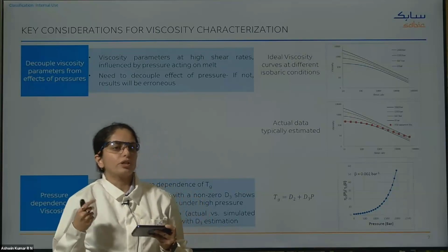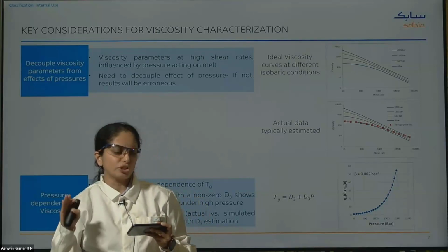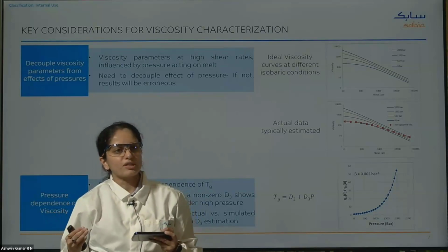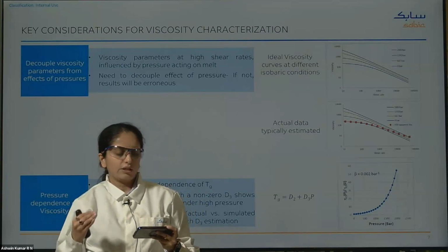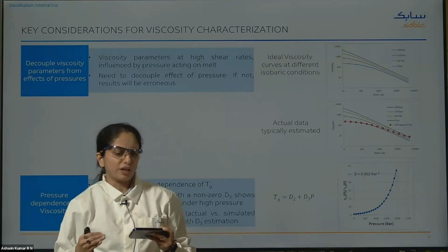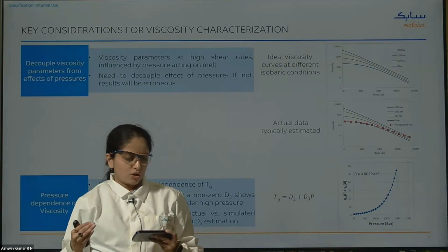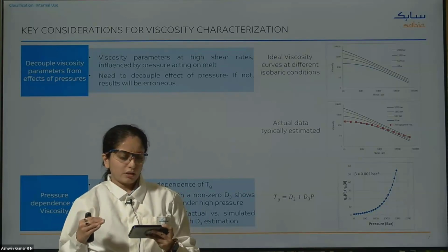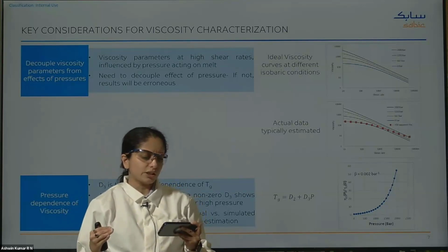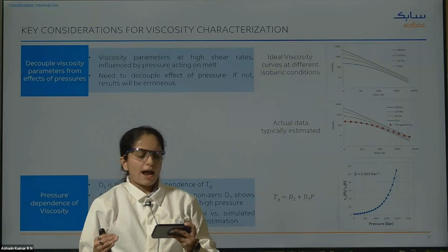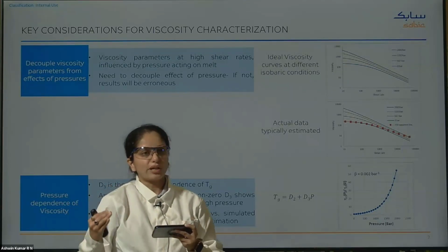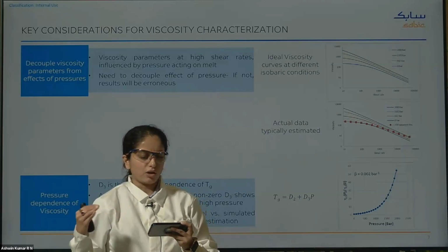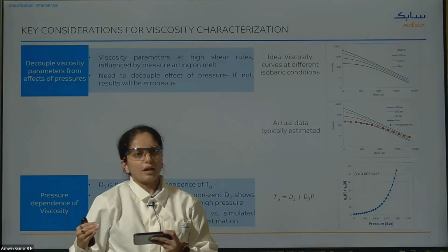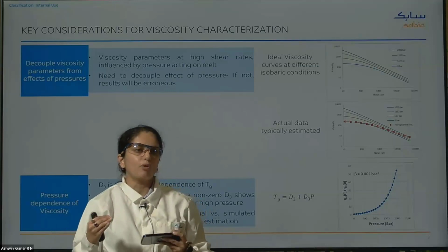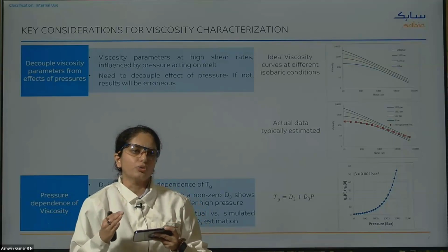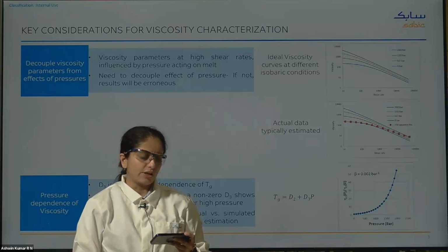I would also like to touch upon the WLF model, which mostly describes the effects of temperature on viscosity. In an injection molding process, when the pressures are above 100 MPa, we need to account for the increased Tg, the reduced free volume, and the effects of pressure. Combining the WLF and the Cross model, we see that the effects of temperature and pressure on the zero shear viscosity are accounted for, and then the effect of pressure on the shear thinning of the melt viscosity. All this can be covered and correlated with the help of Poiseuille's equation, which is generally used to measure the pressure gradient inside the capillary rheometer.